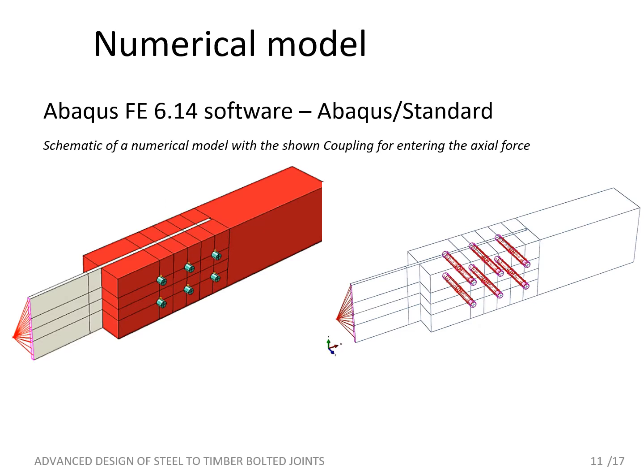The numerical model was created in Abaqus software using the finite element method. The interactions between elements were defined by contact bonds. Models of experimental samples were created in the software to simulate the load action on the samples during the test. In the figures, you can see also contact bonds and coupling for entering the axial force.